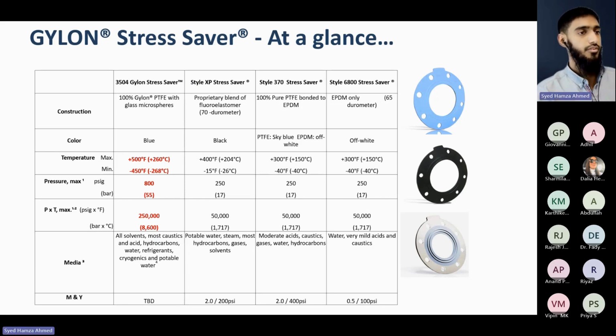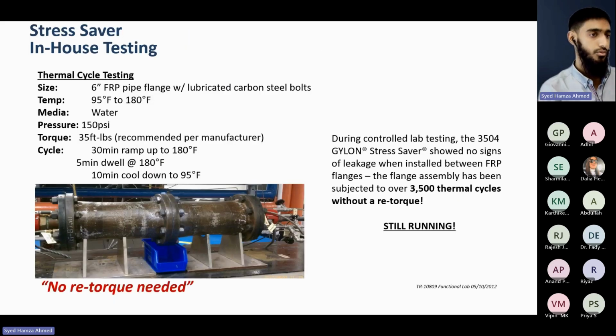So we have done a lot of testing on these types of gaskets. Let's talk about one of those tests. Here we have taken an FRP pipe flange with lubricated carbon steel bolts for this type of flange arrangement, with a nominal pipe size of 6 inches. The temperature was cycled throughout the range of 95 to 180 degrees Fahrenheit, with the media being water held at a pressure of 150 psi.